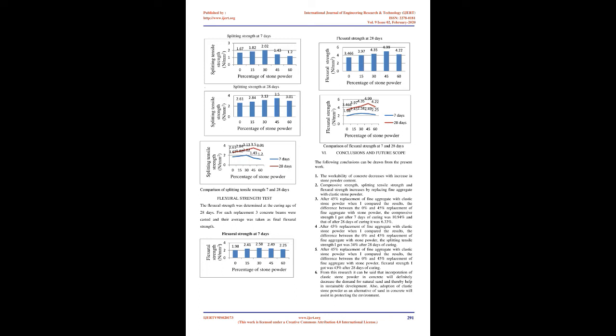Splitting tensile strength test, IS 516-1959. For investigation of splitting tensile strength, concrete cylinders having size 150 mm x 300 mm (diameter x height) were cast, demolded after 24 hours and cured for 7 and 28 days. The splitting tensile strength has been checked at the age of 7 and 28 days. 3 cylindrical specimens were cast for each replacement. The test has been done by compression testing machine (CTM).